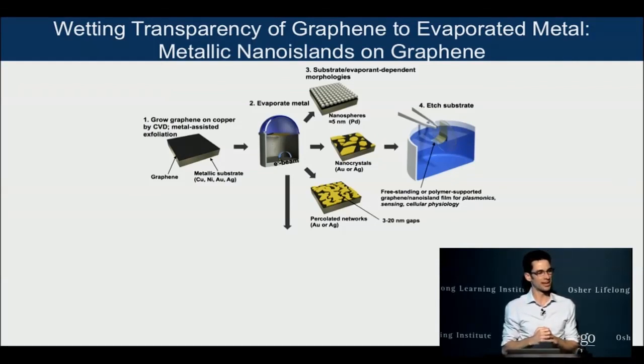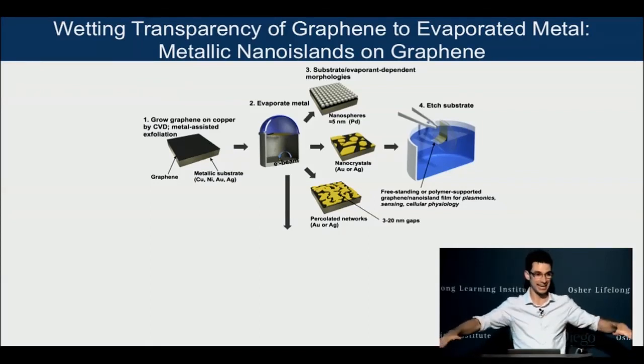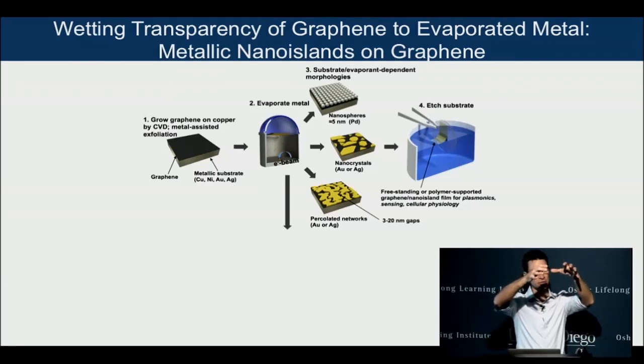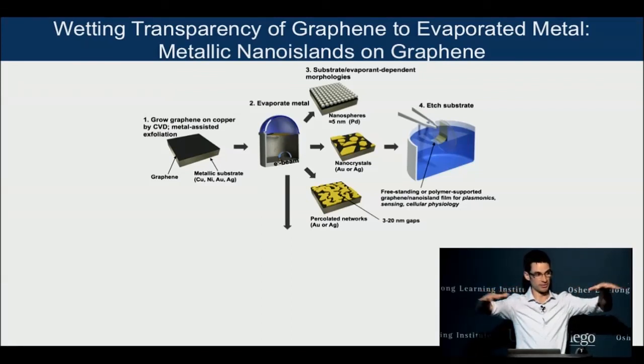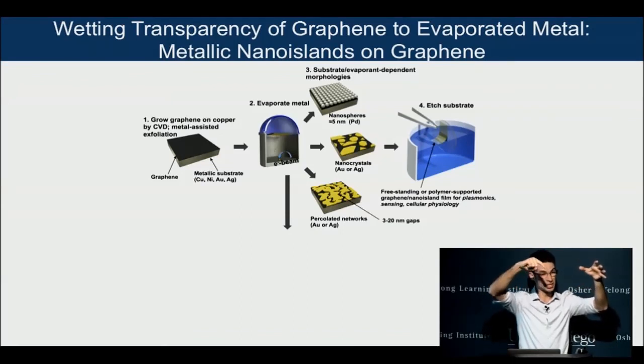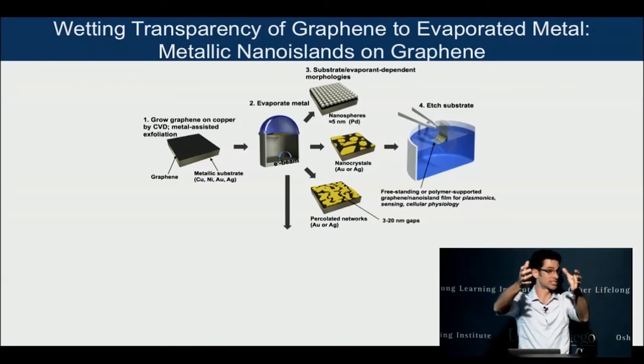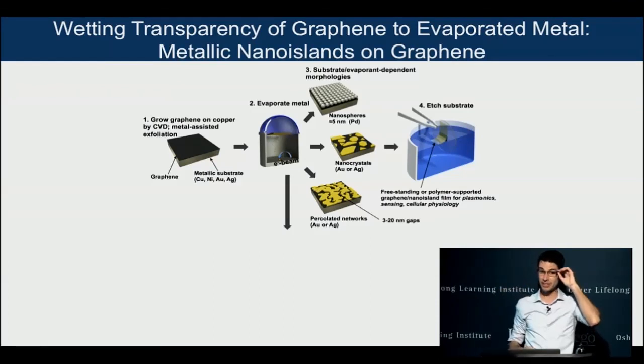It turns out that graphene is a little bit like a Scotchgard coating, but if you change what's below it, so you change the windshield for a different windshield, the ability of graphene to be a Scotchgard coating changes a little bit. If you have something like glass and then graphene, the droplet of water will spread out a little bit. But if you have plastic, then graphene, the droplet of water sees through the graphene and beads up, just like it would on plastic. So that's a really interesting phenomenon.